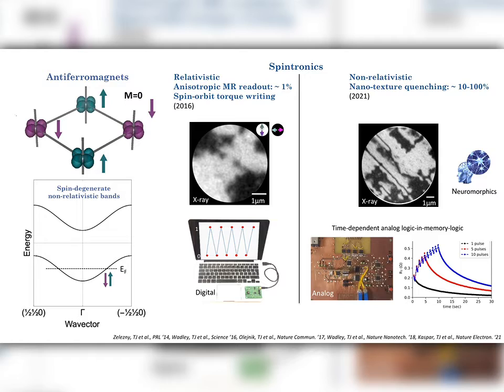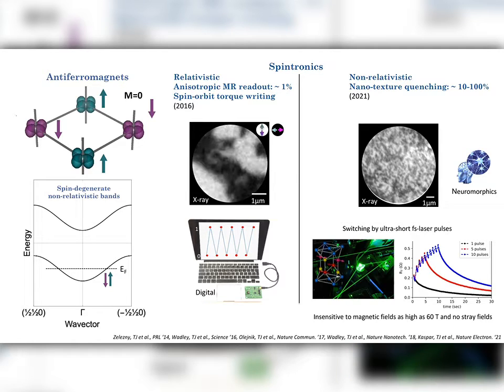So these devices may be favorable for designing not the conventional digital memories, but analog memories mimicking components of the artificial neural networks. With this nano fragmentation switching mechanism, one can replace the electrical pulses also with optical pulses and demonstrate switching scaled down to the ultimate single femtosecond laser pulse.